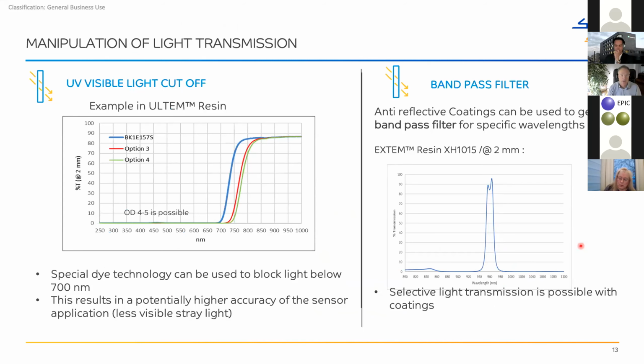This is very interesting. What you can do with any thermoplast is to add a very special organic dye into your thermoplastic material by compounding, and therefore absorb all the visible light. It opens up at 700 or even at 750 nanometers. So it's transparent to infrared light for the sensor, but it absorbs the visible light to a large extent, with an optical density of 5.